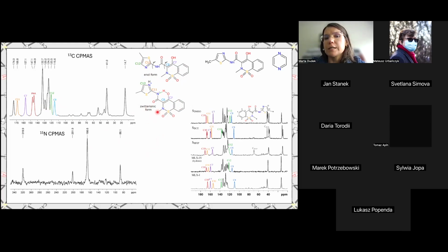In many structures, it exists in this form, for example, in DMSO solvate, or similarly in a hydrate, and you can see that the outlook of the signals that are marked with colors here is different. And this was what we saw in meloxicam pyrazine. So we immediately expected this Zwitter ionic form to be present. We also saw from nitrogen-15 experiments that there is only one NH signal from pyrazine. So we assumed that there is half a pyrazine molecule in the crystal.